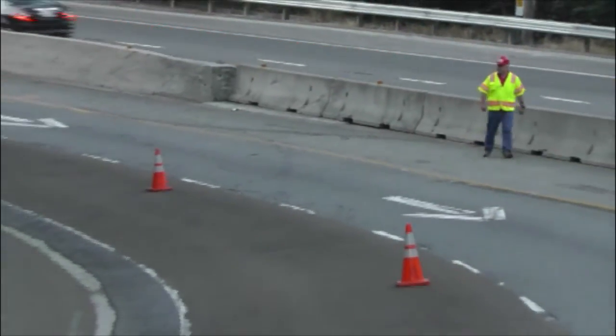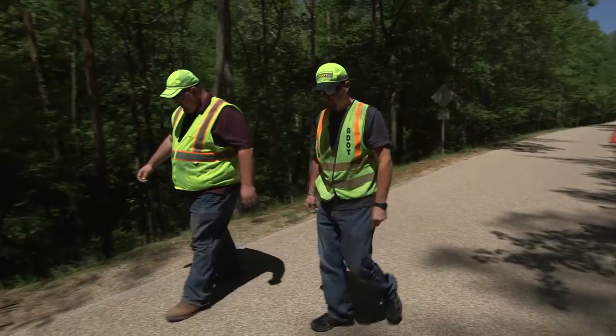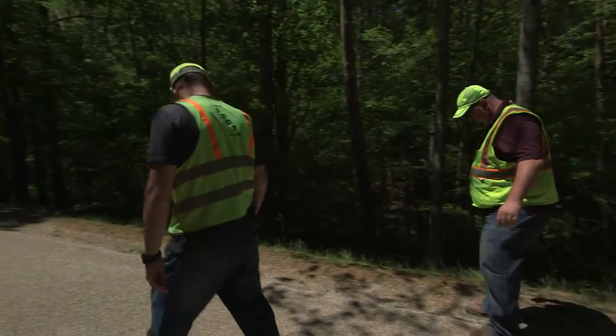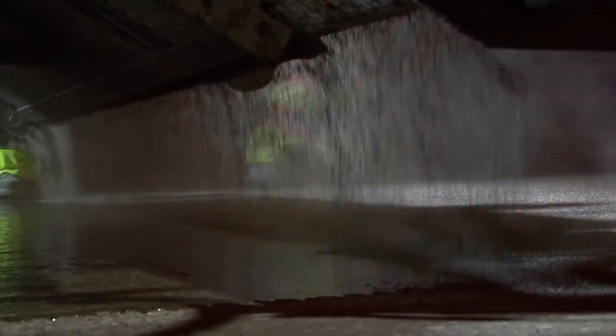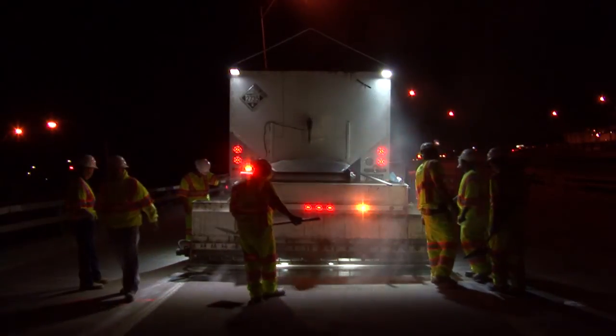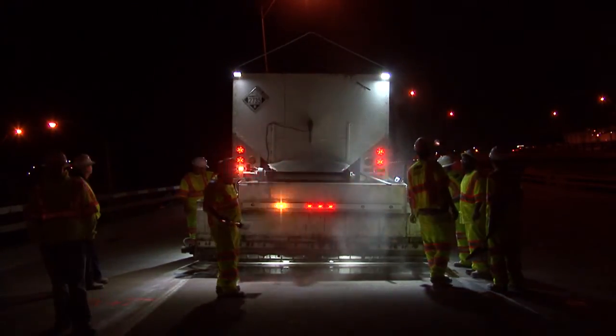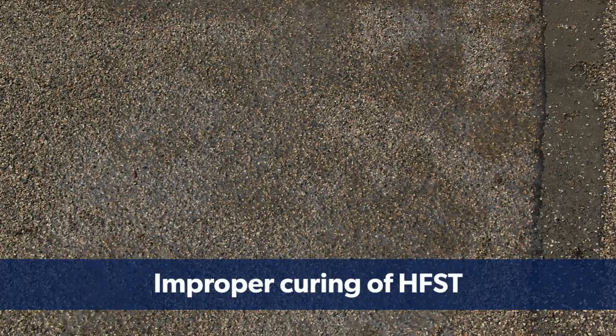A critical quality control step for agencies is to inspect the installation. Some inspections will occur during the project, and some will follow completion of the installation. During the installation process, it is important to inspect for areas where the binder and bauxite aggregate are missing. If found during installation, the areas can be filled to ensure uniform coverage. It is also critical to inspect for areas where the binder has not cured properly and is soft. These areas may need to be repaired or removed and reapplied.